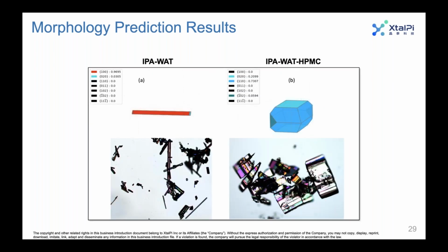Next, we have the IPA water. This is a binary solvent prediction. Experimentally, we get these needle-like morphologies, and they even tend to agglomerate. But the morphology prediction calculation is able to predict those needle-like morphologies. And then we have a simulation that takes into account HPMC. Experimentally, when you do that, you deviate away from the needles and get something very block-like or prismatic, and we're able to reproduce that with the calculations.